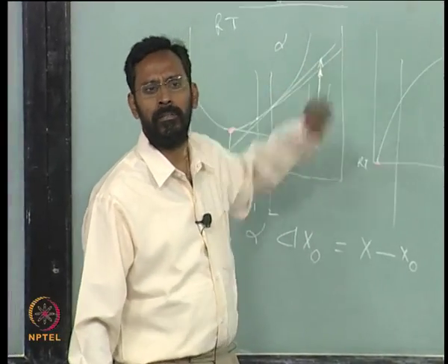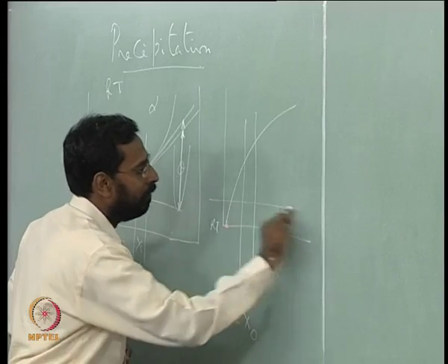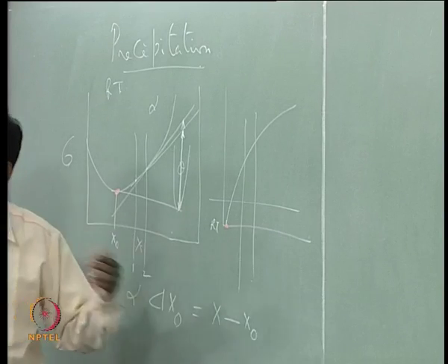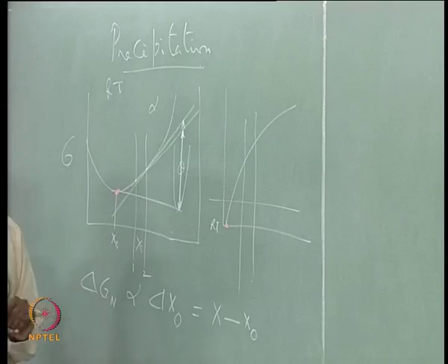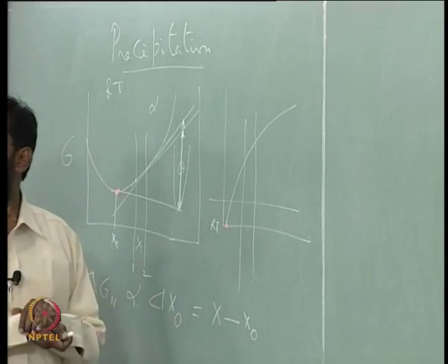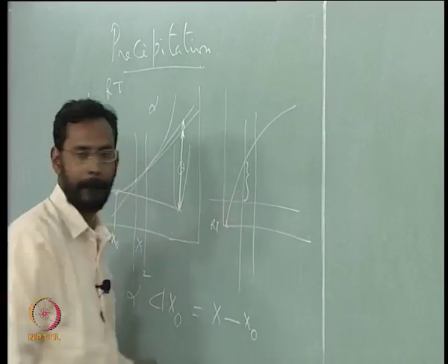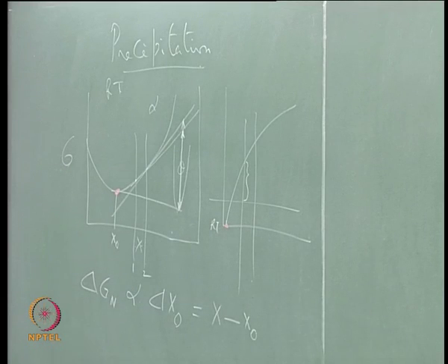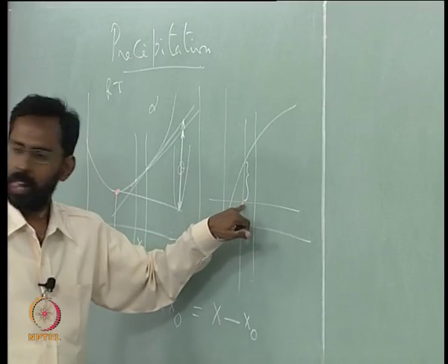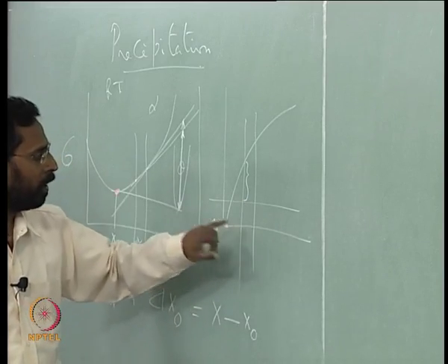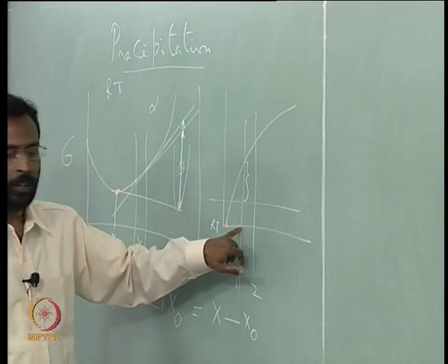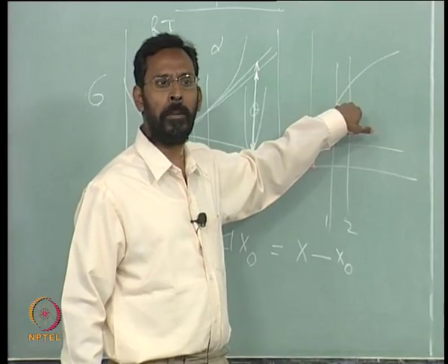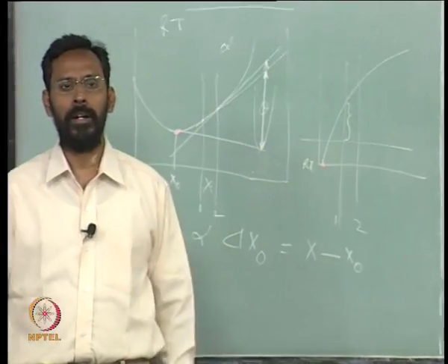I can change the temperature. If I choose some other temperature, there also you would see the same thing. And you can also see it in terms of the phase diagram. What tells you about the driving force is this. This is the actual driving force, not in terms of delta G for that matter. You are at a temperature, for example if I am considering the same room temperature, alloy 1 and alloy 2, for alloy 1 you are at a temperature away from the equilibrium transformation temperature. The moment you are below this equilibrium transformation temperature, there is a driving force for the second phase to precipitate,